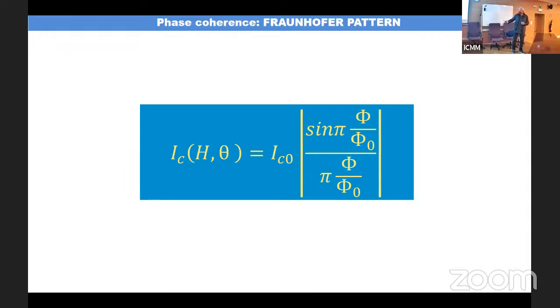In the Fraunhofer pattern, the critical current shows this dependence with magnetic field, this is magnetic flux across the junction, this is the flux quantum. So every time the flux amounts to a flux quantum, the critical current goes through zero, and this gives rise to the Fraunhofer pattern. But remember, the critical current was very small, so measuring it was challenging. If you want to show that there is a modulation of this very small critical current, it's a mess. So we decided instead of measuring the critical current, we measured slightly above the critical current a resistance, which feels the critical current, and we changed the angle of the magnetic field with the direction of the wire.